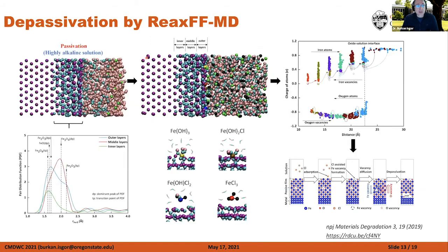We started our research like that, but then we wanted to see what chlorides do to this passive film, so we added chlorides into the electrolyte and saw what happens. Now, this is a very big topic to cover, which I'm not going to be able to do in this short presentation, but some big messages here are that a little chloride doesn't do anything. So chloride content is important to initiate a process. The pH is important. How much OH you have in the electrolyte is important. What Ueli mentioned, the chloride to hydroxide ratio, is very evidently shown in these simulations as a critical factor.